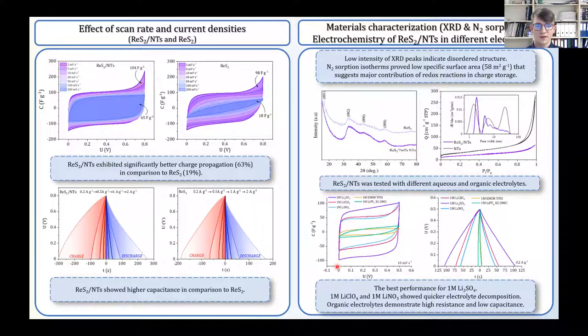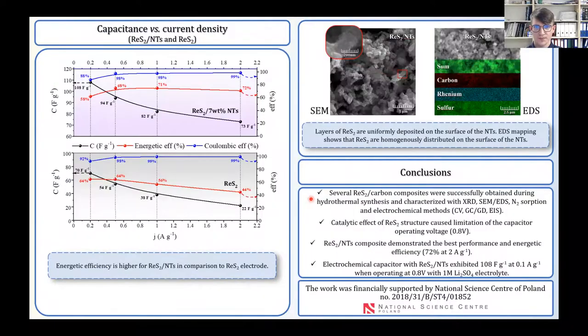Later we have decided to compare this material in different electrolytes. For example, it occurs that the best performance was reached for 1 molar lithium sulfate. Here you can see that not only the capacitance was improved, but also the energetic efficiency for this material was improved by about 30%.